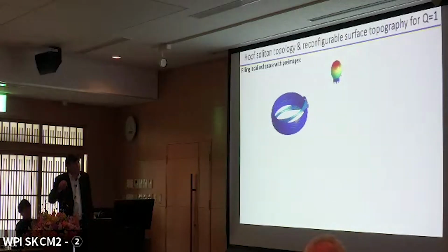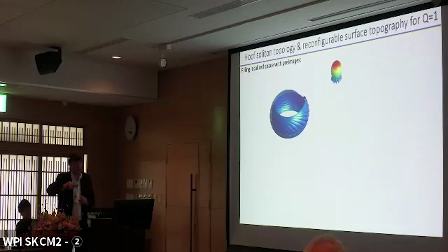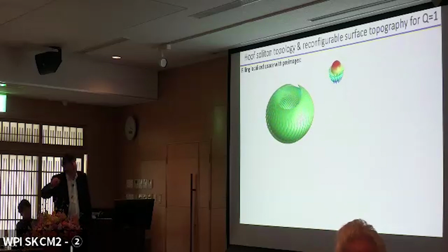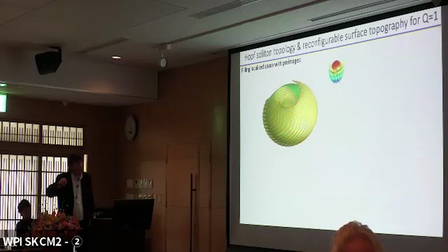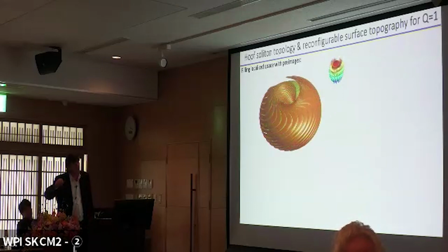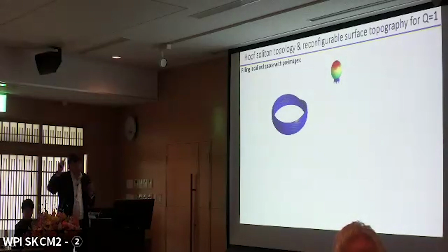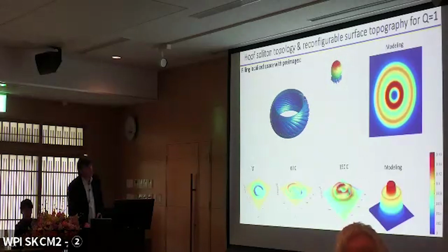So now in our three-dimensional topological soliton, we have all possible orientations of director, and for every single orientation of vectorized director, we have a pre-image with the shape of closed loop, and these pre-images tile themselves for every constant value of polar angle into tori, whereas the smaller tori nest inside of bigger tori all the way until the north pole of this S2 order parameter space of vectorized director field, where in its exterior the director is uniform and the interior are all possible orientations of director field.